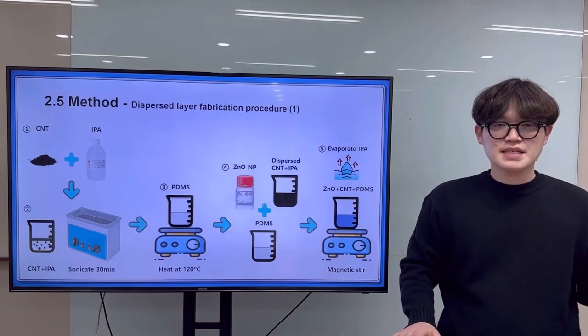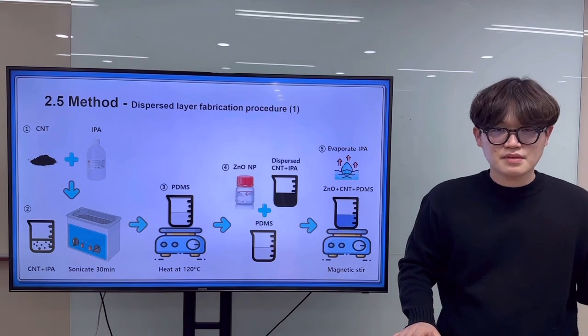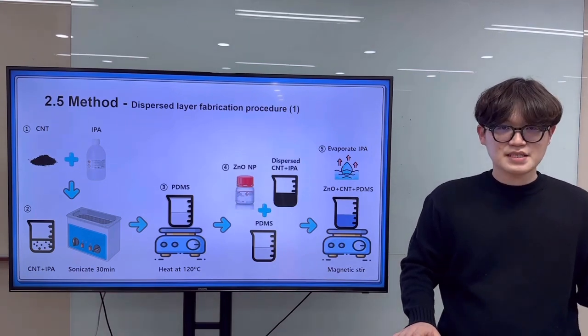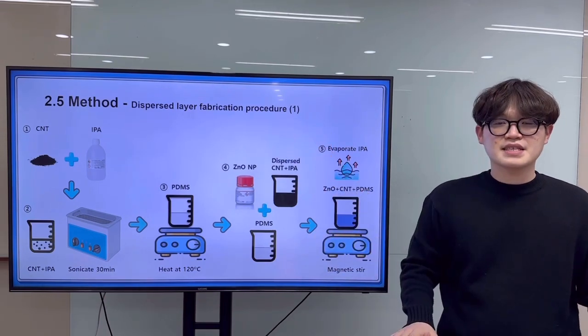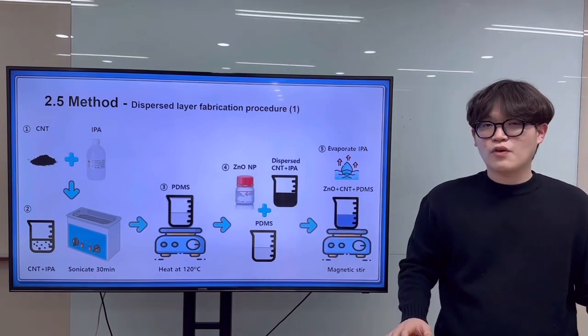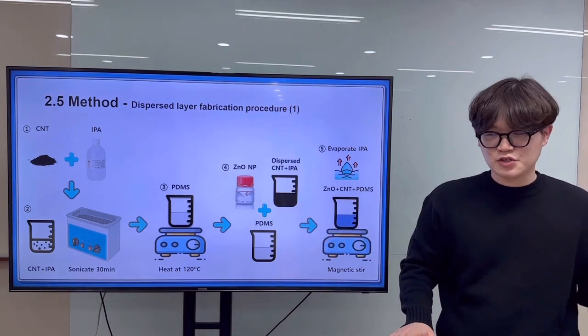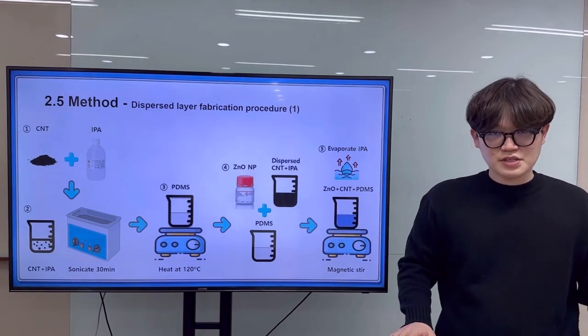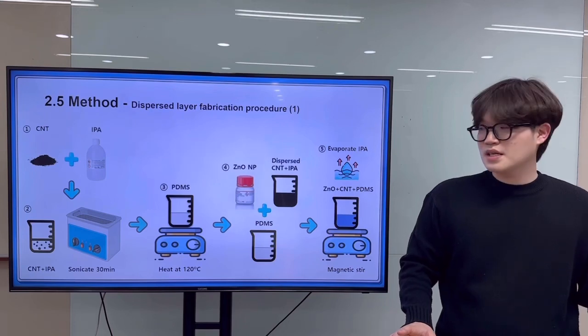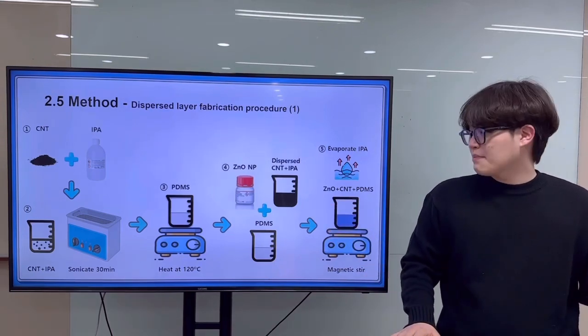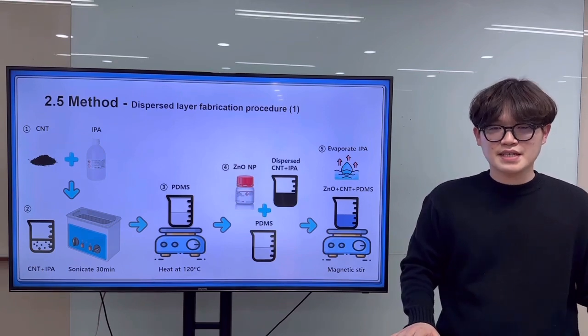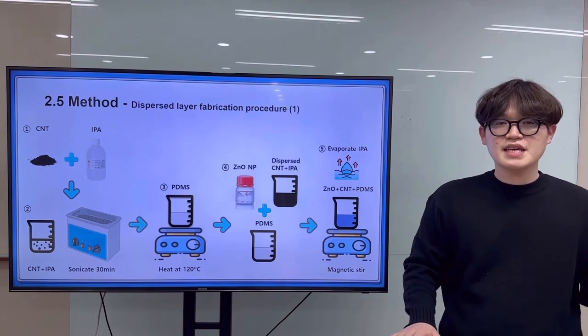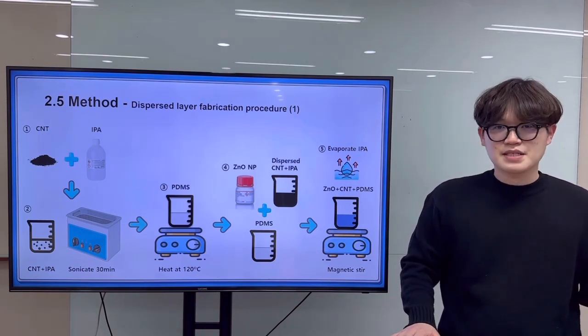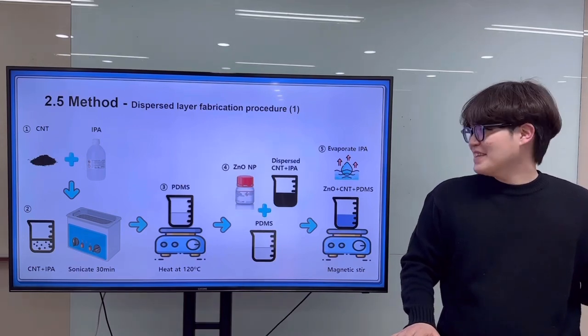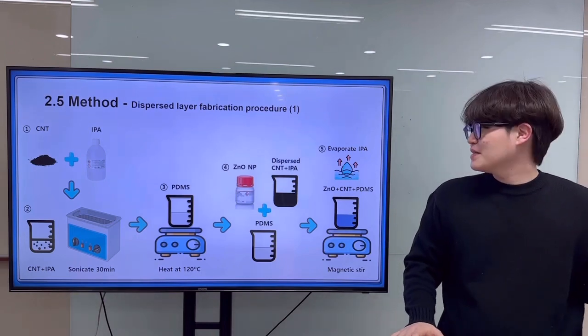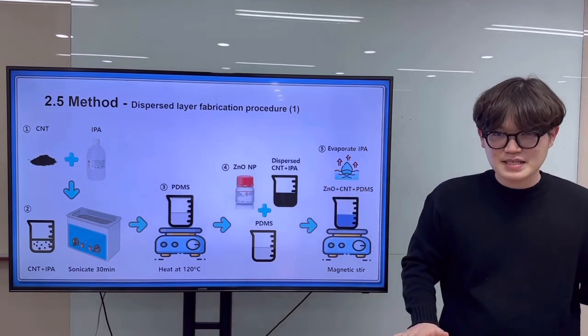Next, we mix zinc oxide and CNT with PDMS to put them on the substrate. First, add IPA until CNT sinks and put them in a sonicator for about 30 minutes at room temperature. And then it makes CNT dispersion better. During dispersion, heat PDMS on a hot plate at 120 degrees Celsius to reduce the viscosity for about 20 minutes. And then we put zinc oxide nanoparticles, CNT and IPA into the heated PDMS.